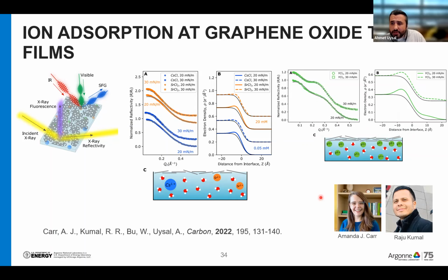But this first study was very difficult. We had a very hard time getting stable and reproducible graphene oxide films at the air-water interface. It wasn't very easy. And one reason is graphene oxide is not a perfect amphiphile like the other surfactants that we are using. It has some amphiphilic character, but when you're spreading, it is very possible that some of the graphene oxide is dissolving in water actually, and therefore creating a nice film is not easy.